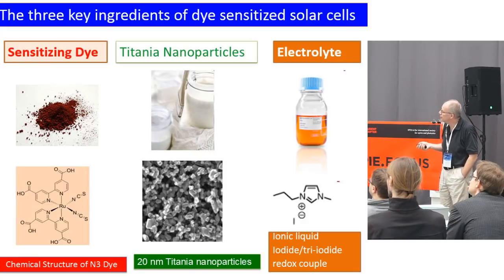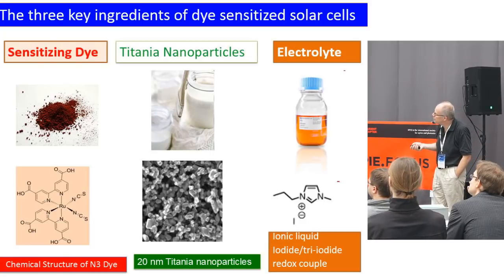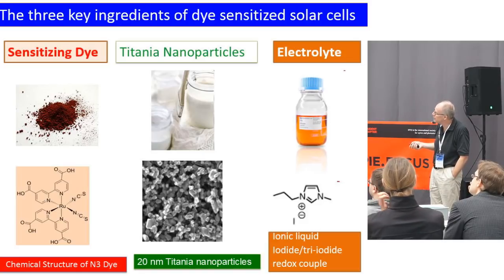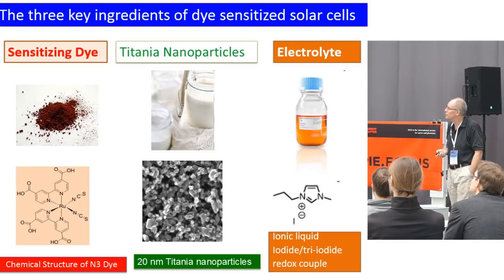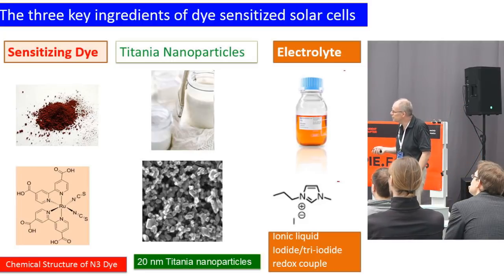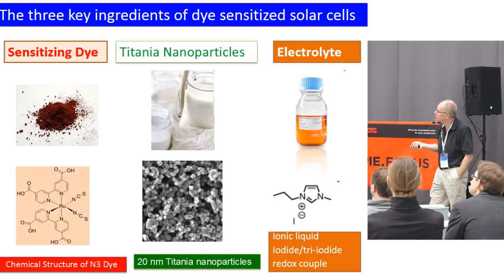The typical dye was a ruthenium complex, so it's a ruthenium metal with bipyridine ligands, as we call them, and they also have these carboxylic groups, and these thiocyanate ligands were introduced by the Grätzel group. This became the standard dye for 15 years, I would say. Although thousands of dyes were synthesized and published, this was one of the first ones, and it was the best one for many, many years. It's interesting to think why it took so long to find something. We have something better today, but this is a standard dye.